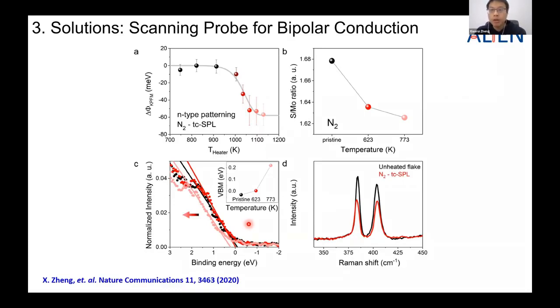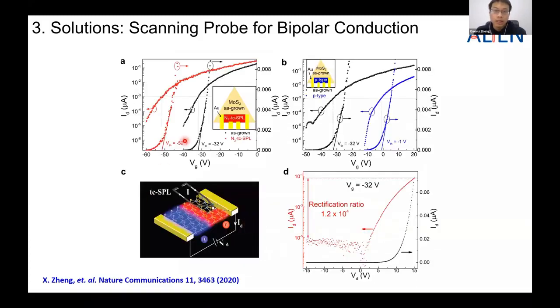Okay, so far we are able to achieve both n-type doping and p-type doping by simply tuning the gas environment of the chamber. So the next step we could do is a p-n junction. Firstly, we prepare a pristine sample and we dope the entire channel to n-type, and you can see the transfer curve. The threshold voltage has been shifted to the left. This is a proof of the entire n-type doping of the channel.